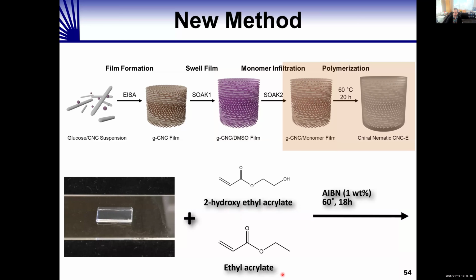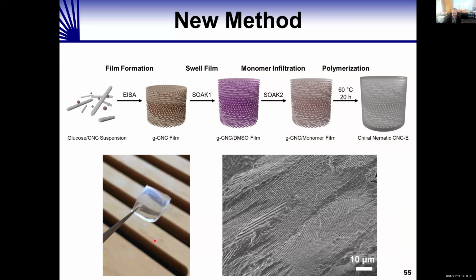We add an initiator, a thermal initiator in this case called AIBN. Again, just something that we buy. And then we heat the film at 60 degrees for 18 hours. And what we get is a colorless, transparent film. This is a mixture of cellulose nanocrystals and our elastomer.